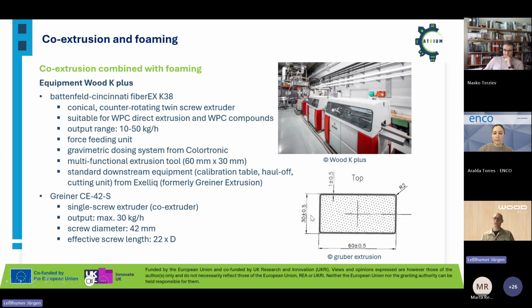And this is the experimental tool we use. It has the dimension 60 by 30 millimeters, and the thickness of the shell layer in our case is 1 millimeter. So we have to add these cost-expensive additives only in this 1 millimeter thick surface layer and can use recycled materials and cheap materials for the core layer.